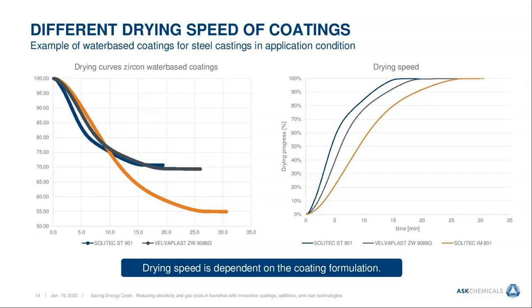What about the different kinds of coatings? Here you see on the left graph the orange curve, and you can see that the drying is finished after 30 minutes. And there are other coatings, for instance, with the blue bar, the Solitec ST901, the drying is already finished after 15 minutes. So that means you save 50% of your drying time. This you can use to reduce, for instance, your drying temperature again and save energy, as already described before. And it has been proven that this fast drying coating is capable even of substituting alcohol-based coatings in a drying oven.